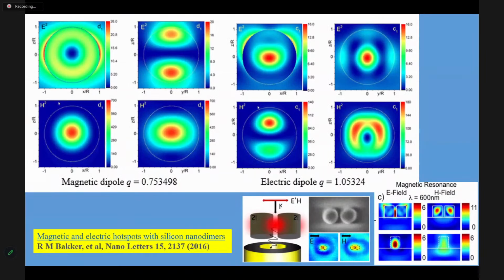So the idea was, and it was shown experimentally, that if you take, for example, 2 cylinders, then between the cylinders you can see field enhancement. It depends on polarization. If it is polarized in this direction, you can see electrical field enhancement, but in the perpendicular direction, you can see field enhancement due to the magnetic field. And it was done for the first magnetic dipole resonance, so field enhancement was above 10, so magnetic intensity was about 100.